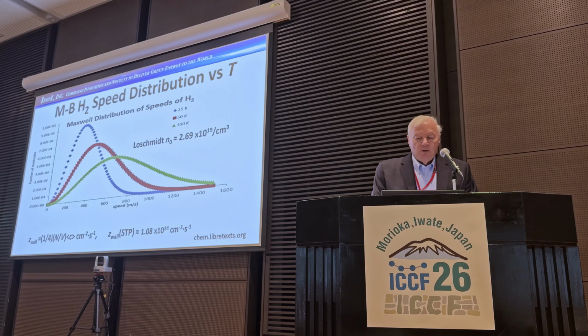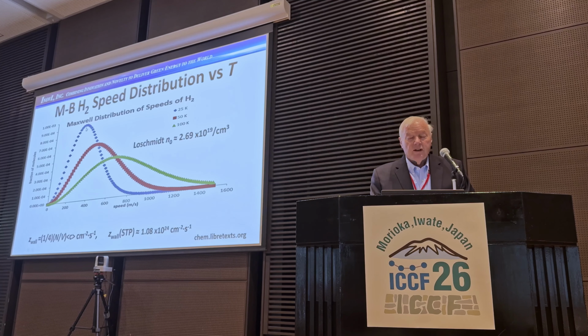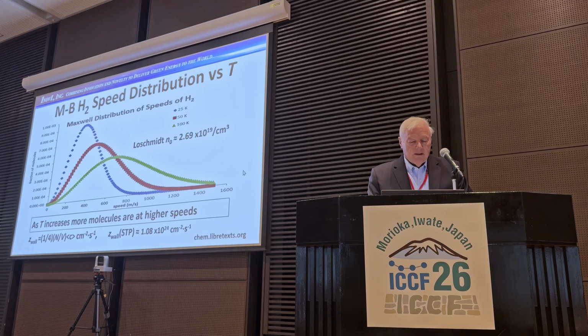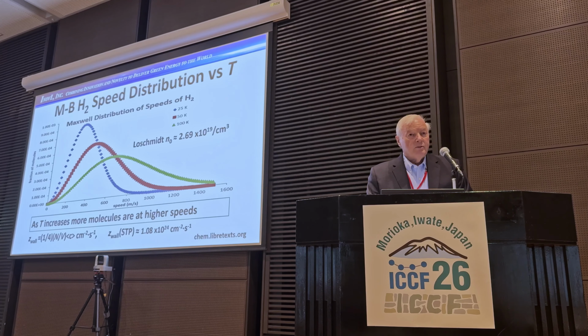Okay, here's the Maxwell-Boltzmann speed distribution for hydrogen. The blue line, these are all cold. The blue line is at 25 Kelvin, the red is 50 Kelvin, the green is 100 Kelvin. So if we're even at room temperature, we're down here, and the tail goes out considerably farther as the temperature heats up. And as it increases, there are more molecules with enough energy that they can knock things off, and we're having 10 to the 24th impacts per second per square centimeter against the electrodes. So even though we're down by several orders of magnitude, we have a big number that we can apply to the problem. And here's the energy distribution.